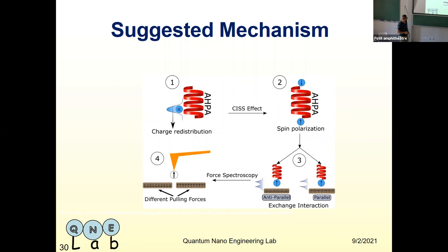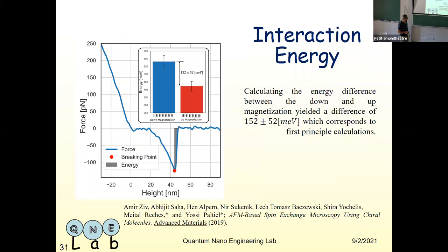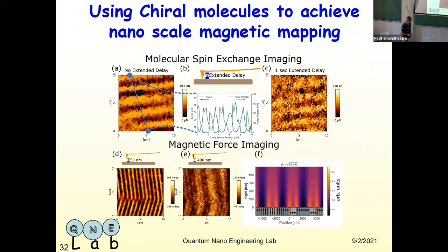So again, this is the experiment. This is the force. And if you want to measure the difference in forces, it's about 150 millielectronvolts in energy. You take the integration of the force over the distance, so you can have an energy scale. And this energy is about 7 times the room temperature energy. It's quite high. The exchange forces are quite high. So it's quite strong.